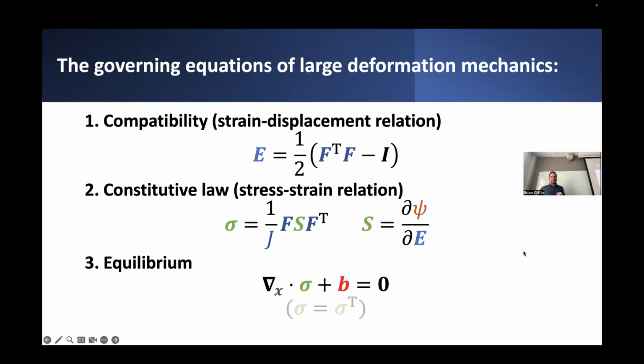All of our different expressions for the governing equations of mechanics, now in the presence of finite deformations, are complete. We've figured out our revised strain displacement relationship in terms of this Green-Lagrange strain measure. We've come up with our new constitutive law that involves, again, a second Piola-Kirchhoff stress that's derived directly from some postulated internal strain energy function that might depend on the Green-Lagrange strain measure. We have a way of transforming that second Piola-Kirchhoff stress into an equivalent Cauchy measure of stress. And finally, we have equilibrium, which is expressed directly in terms of the Cauchy stress, as defined relative to the deformed configuration of the body. So it all came together.